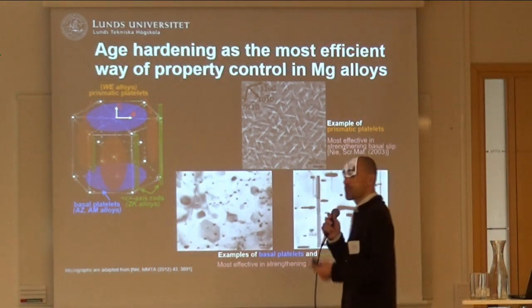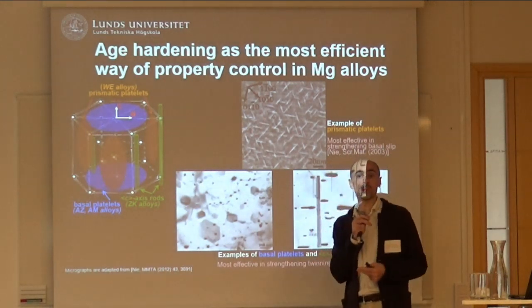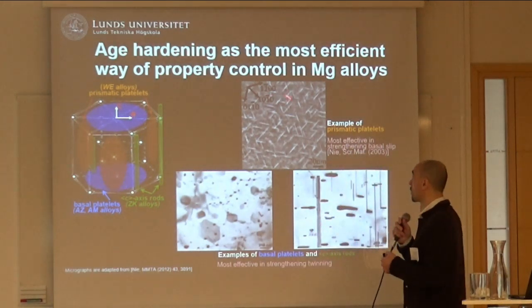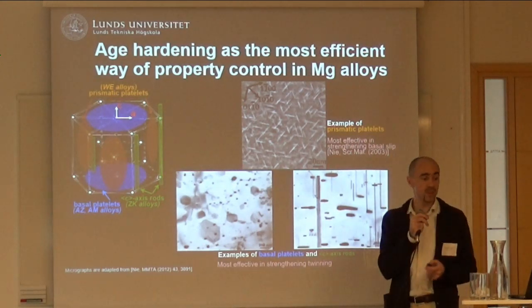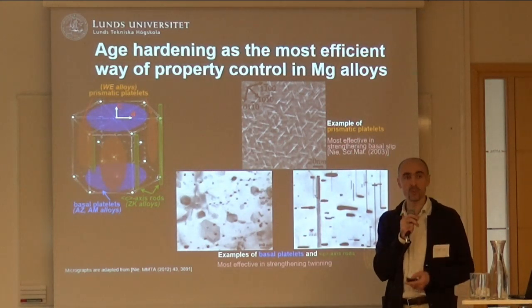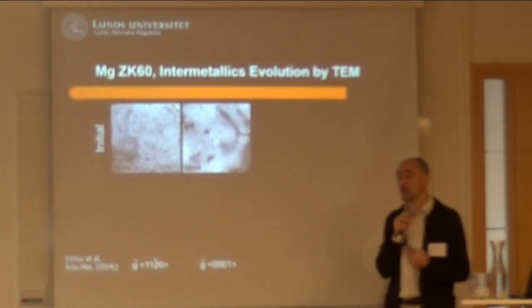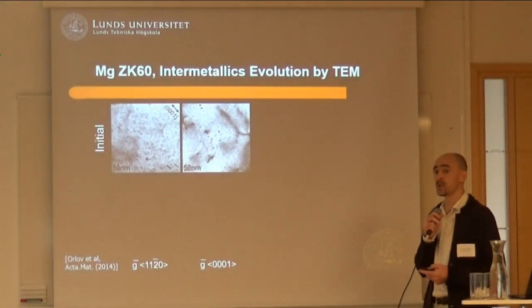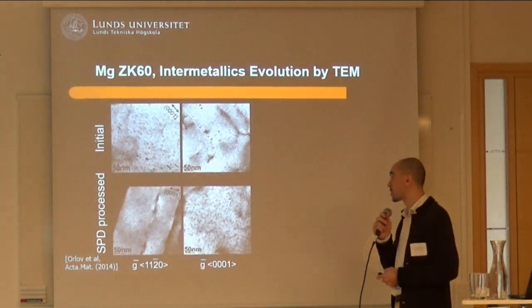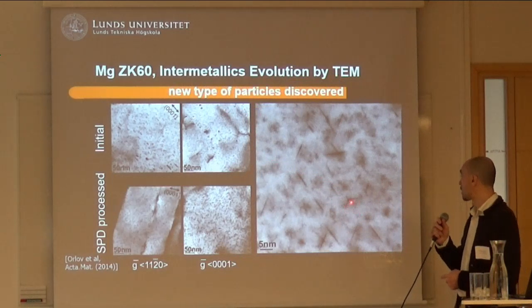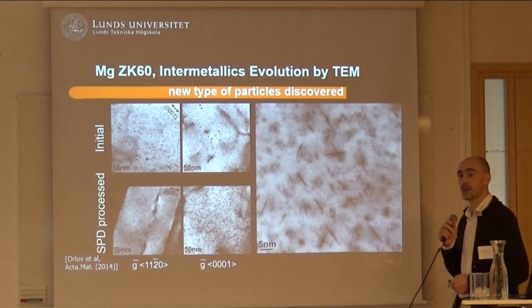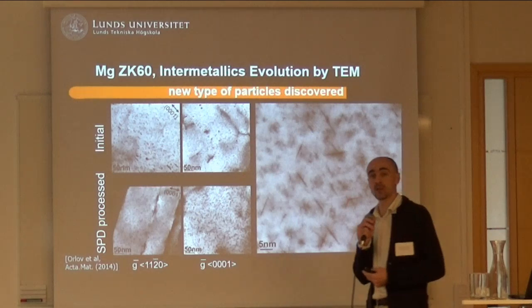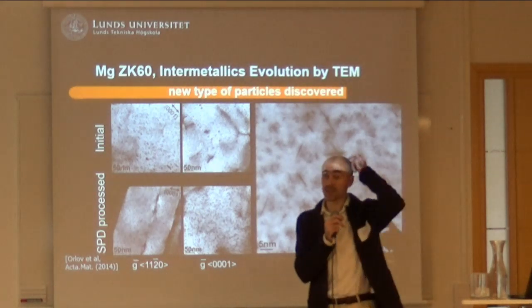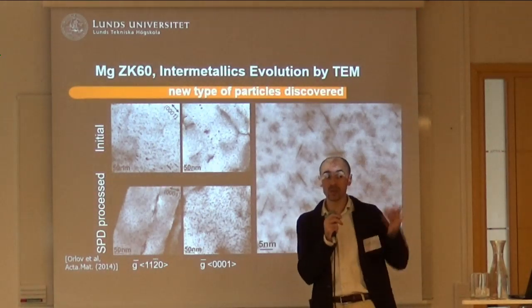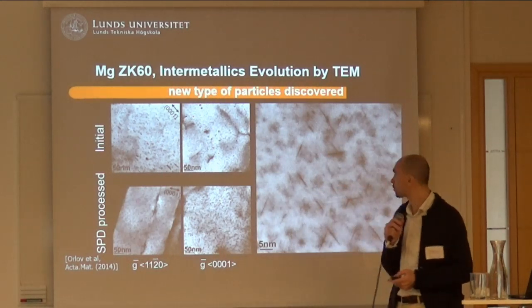What we've done with this ZK60 alloy, which is a zinc zirconium alloy without rare earth, we developed this type of precipitates. We discovered that in our alloy, when we do the processing which we could do, in general, zinc is the precursor for such features in the microstructure. What we found with transmission electron microscopy in the lab is that we can develop this type of precipitates right here, like this, that are more common for rare earth containing alloys. We found it in a system without such. So we don't need to compete, for example, for rare earths.